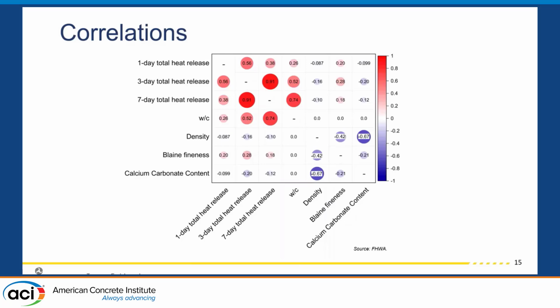Once your reactions are happening, anything that's happening in those later ages is highly related to how much water is left in the system to cause reaction. And then our density and our calcium carbonate content had a pretty high negative correlation. And once again, that makes sense. Our calcium carbonate, that's somewhat limestone, and that has a lower density. So we would expect to see this lower density.